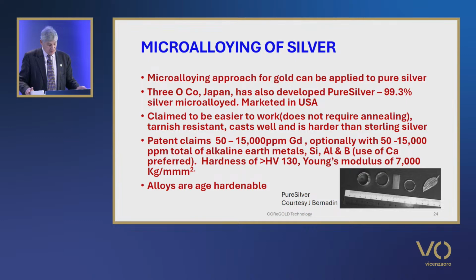A further embodiment of the patent claims an alloy of at least 99.45% silver with 50 to 5,000 parts per million of gadolinium, plus further optional additions of the same metals. Hardness values of at least 120 Vickers and a Young's modulus of 7,000 kilograms per millimetre squared are claimed, with hardness rising to at least 140 with 50% cold work. These materials are claimed to be heat treatable. The use of gadolinium is claimed to be the most effective hardening element and results in a high Young's modulus. These small additions do not affect the colour.